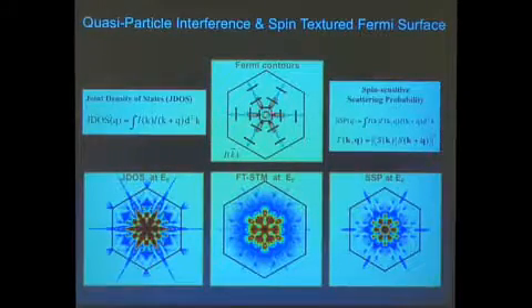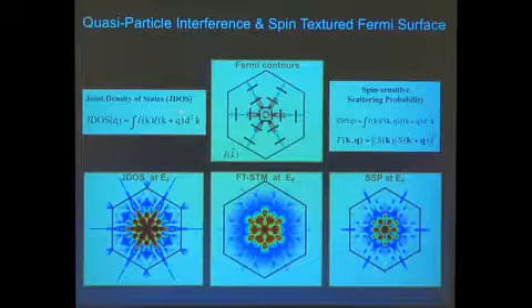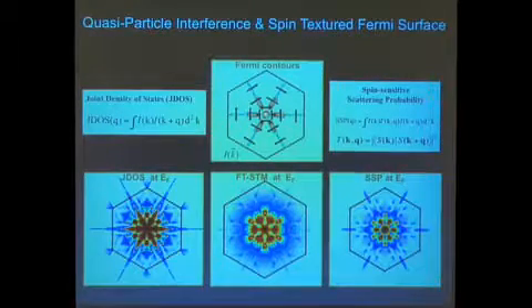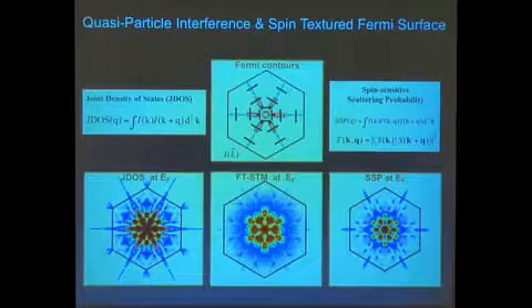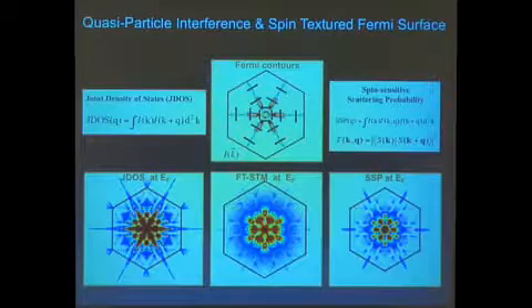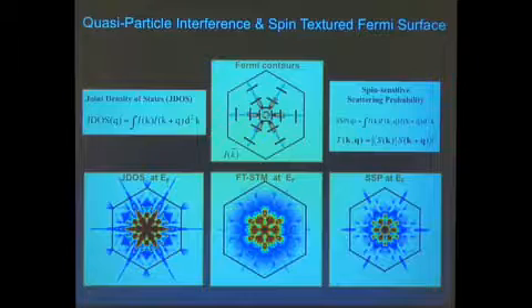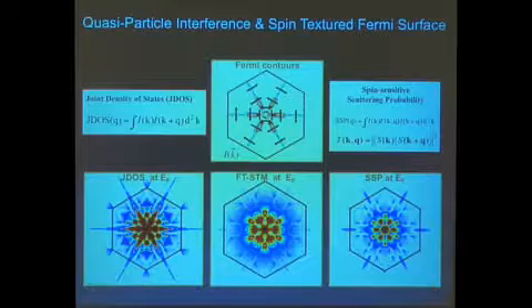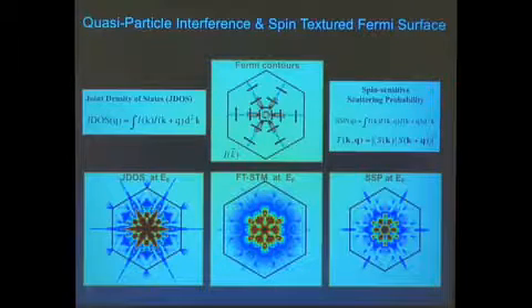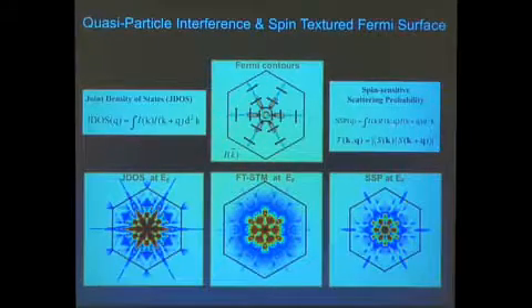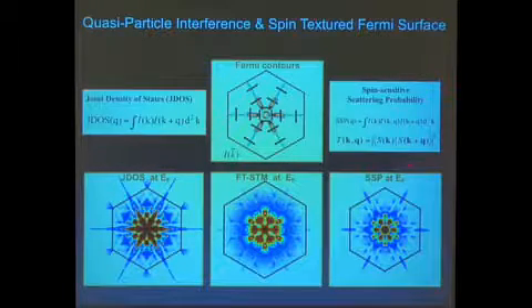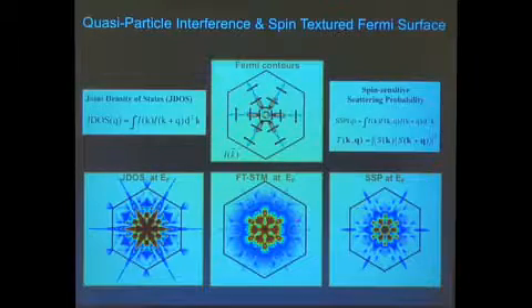So where did I get the radial dependence? Why this is going this way and that's going the other way? Yeah. So we knew from photo emission this one was going one way and that one's going the other way. We didn't know anything about the other circle because that's not measurable from the photo emission experiment. But we know that this is a topological insulator from the band structure calculation. So we make the assumption that this has to go the other way. Otherwise, we don't have that information. And in a sense, that's what we are testing in this experiment. So if you put that into the data, you also have to look at the way in which the spins are allowed to scatter. Obviously, you cannot scatter from this state to that one. If you include that, you see that you start to match the experimental data in all its great details.